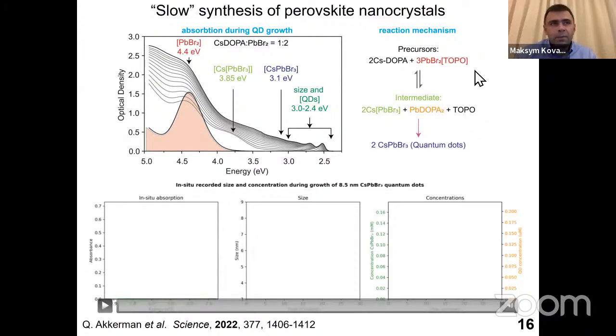The beauty here is that for lead bromides, you can actually observe all the relevant species in situ during the synthesis. The precursor itself, then at slightly smaller energies you observe this intermediate, and then finally you observe the quantum dots. And so just by measuring the in situ optical absorption spectrum, you can recalculate these features, their optical density, into the population of every species, so you can track the mechanism of the reaction.